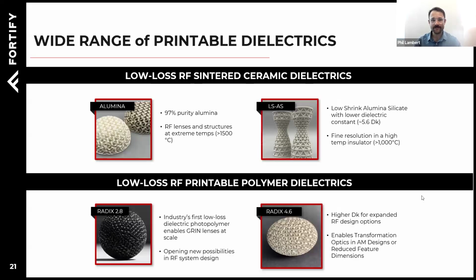Well, Fortify offers 4 materials right now that fit into this landscape. On the top, we have our sintered ceramics. Our most commonly used sintered ceramic is alumina. It's a 97% pure alumina that gets sintered at 1750 Celsius. Tend to have operation temperature somewhere in the 1400 to 1500, depending on what type of thermal environment you're exposing it to. And then on the right side, we have a newer emerging material called LSAS.